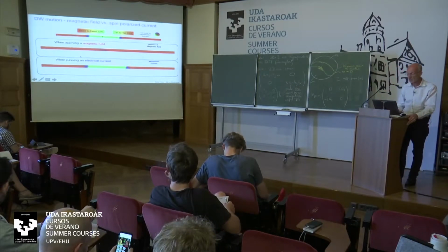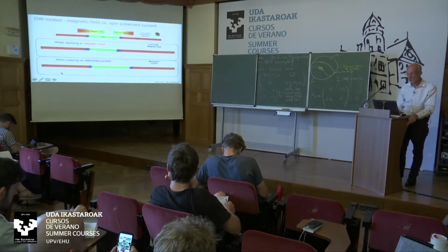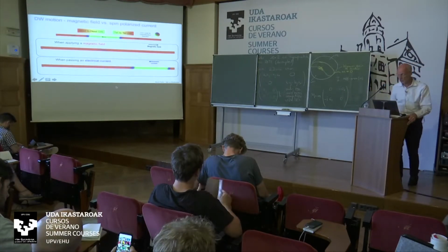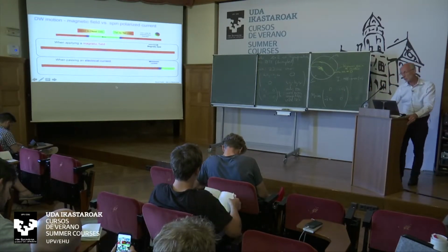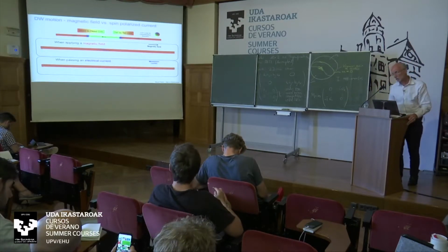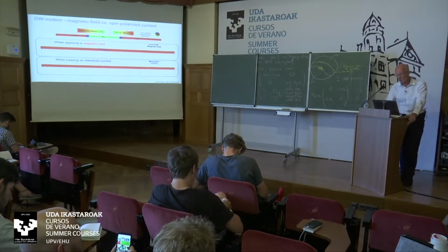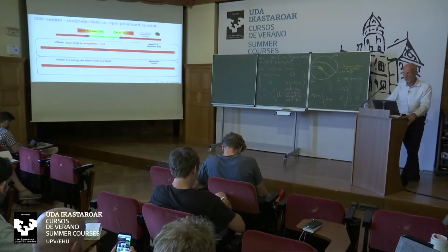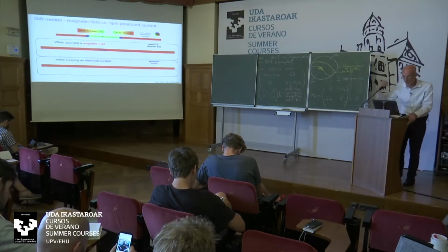However, what's really interesting is that if you pass a current into the same wire, through the mechanism I just briefly discussed, these two domain walls will move in the same direction, because the current is locally spin polarized and basically passes that local spin polarization into the domain walls. This is the concept.